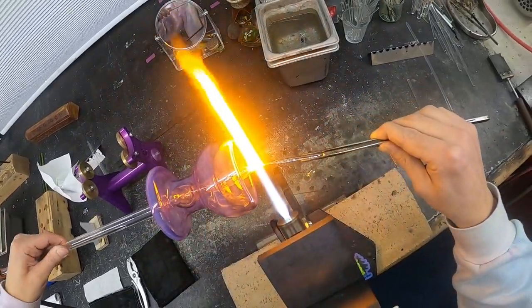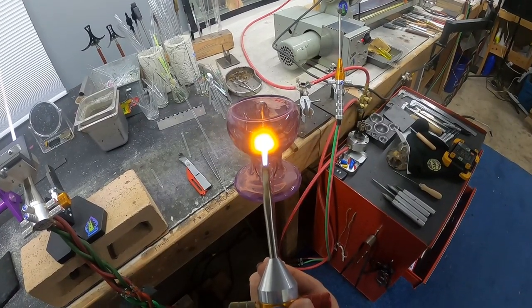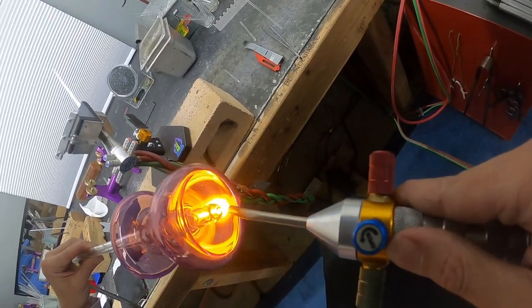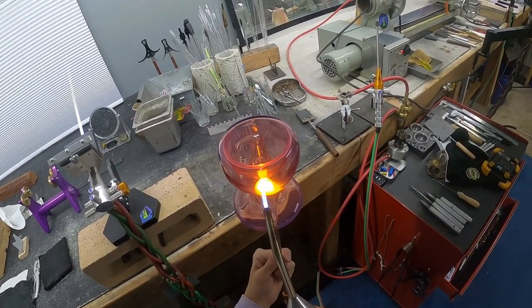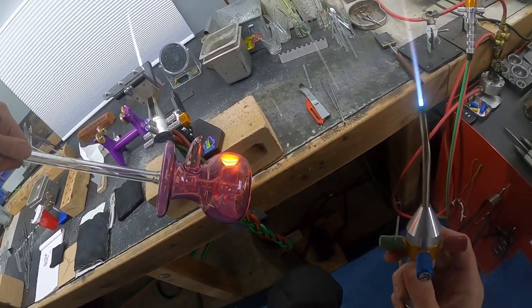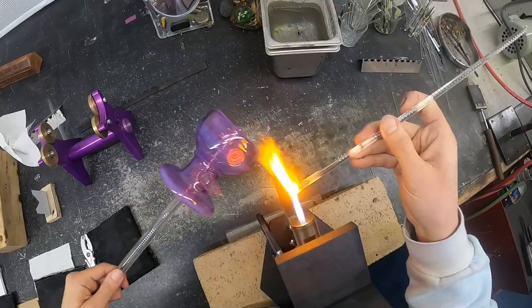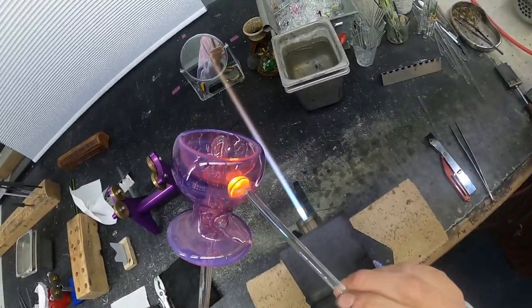We're going to pop our exo holes here. I kept this one in a little long — I'm going to show you two holes, two different ways, so if you have issues with one you can always use the other. You really just want to start by piercing a hole. Heat it up and suck in — you're not actually making a hole, you're making a concave divot. Then I hit it on the back side and suck in just a little bit. I usually let the front do the touching, so I wait until the front is really really close, then hit the front and suck in, and you'll see it slam against the little post.